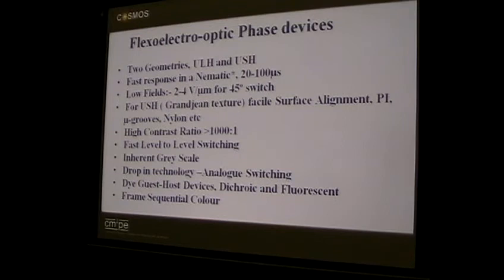Okay? So, flexoelectric devices, two geometries: uniform lying helix, that's the coil in the plane of the device, the spring on its side, if you will, and then the uniform standing or so-called Grandjean texture. What you've got in those devices is fast responses, which leads you to frame sequential color, and very low fields for 45 degree tilt. In fact, it turns out that in the uniform standing helix, you don't need fields as high as that to actually see the optical effect you want.